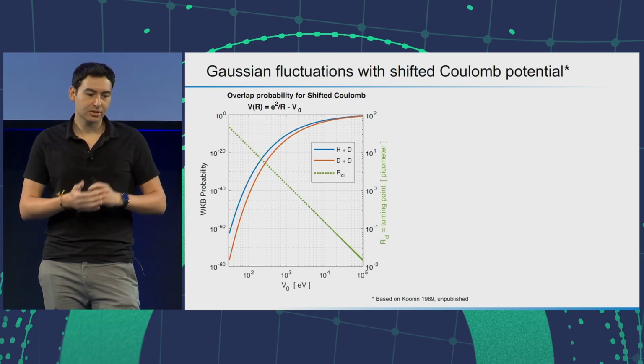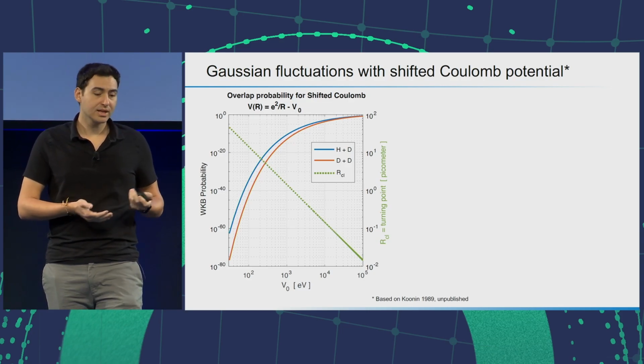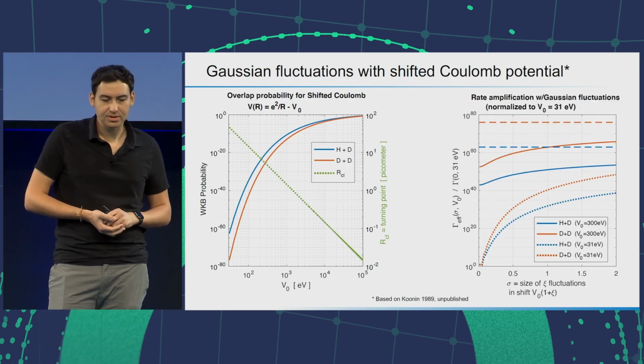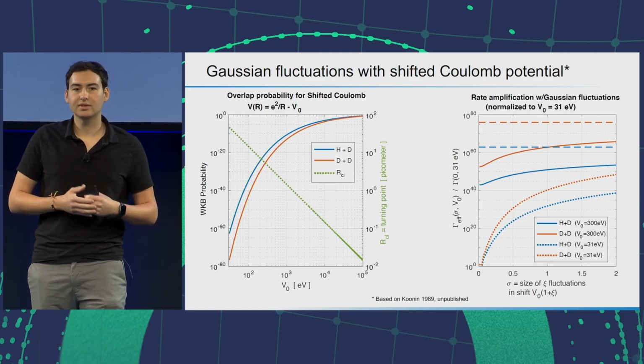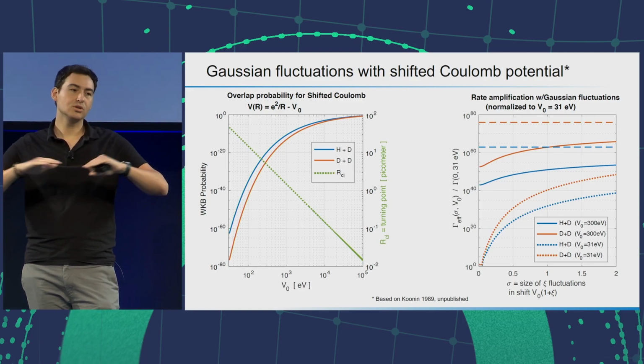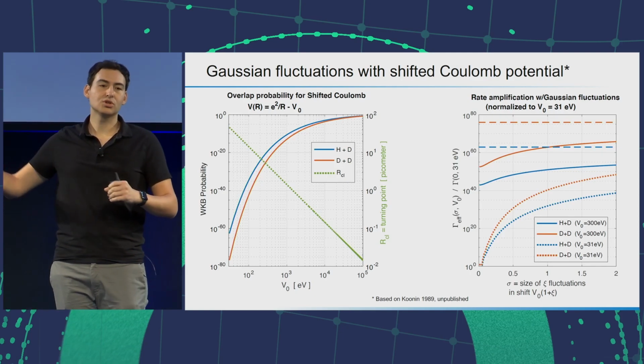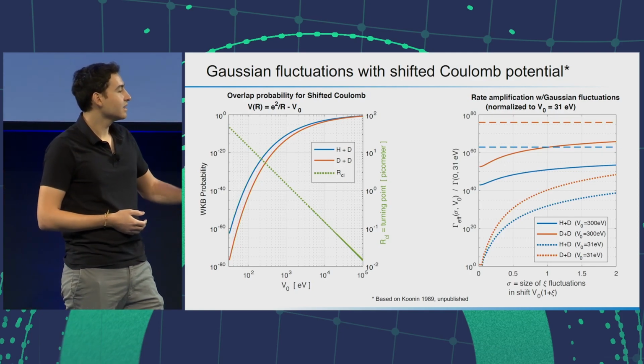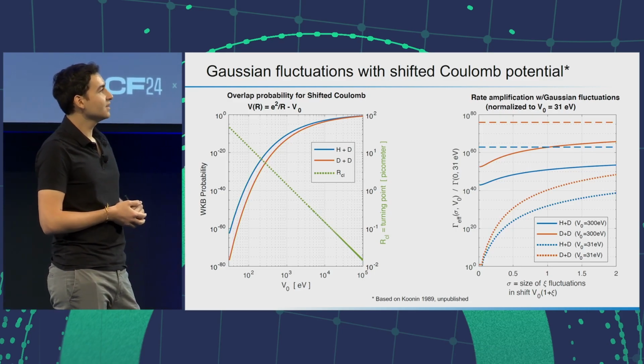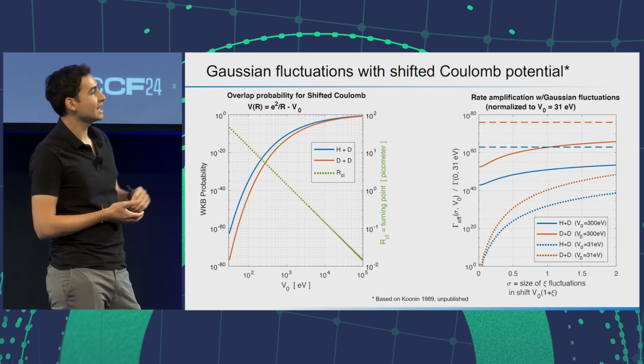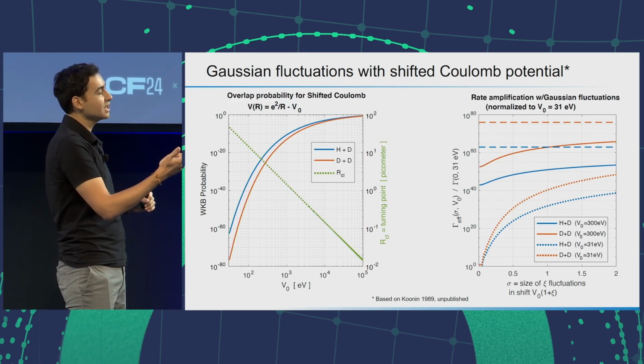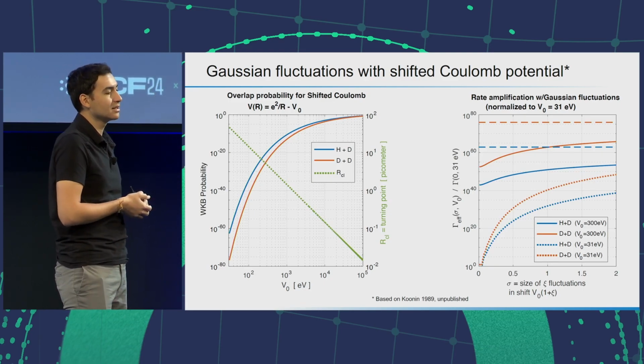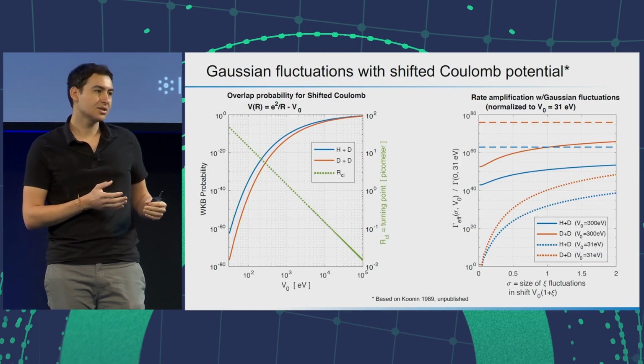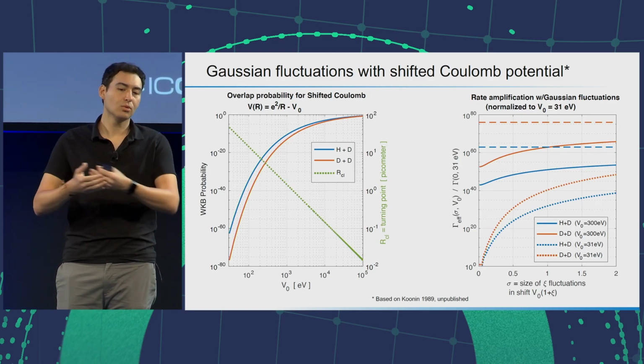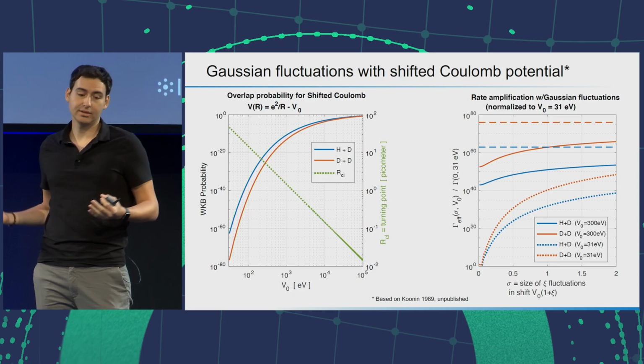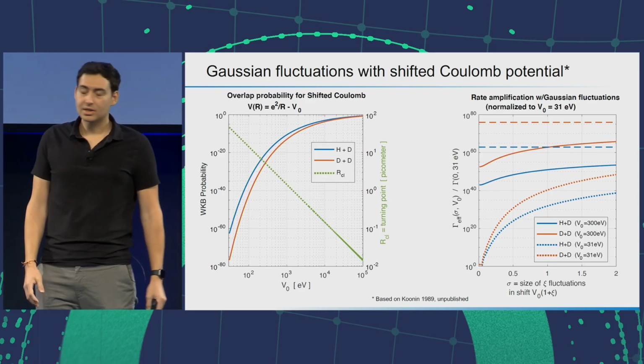And what Koonin did was, starting with this equation, or this numerical result here, he said, what happens if we introduce fluctuations in this parameter? What if it's not a uniform screening value, but it's a distribution of screening values? And the idea is that because of this exponential sensitivity the tunneling probability has to this screening energy, a small increase in the screening energy results in a large enhancement of the tunneling probability. And so there are rare configurations where you have a large screening energy that can overwhelmingly contribute to the net effective reaction rate. And so that's what's plotted on the right side.